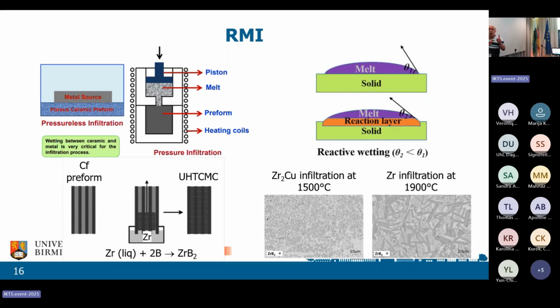So this was one little idea. This research was done at DLR in Germany, and they had one idea: let's put some copper in there, because if we have a zirconium copper alloy, that will now melt at 1500, and they get a much better, much finer microstructure.